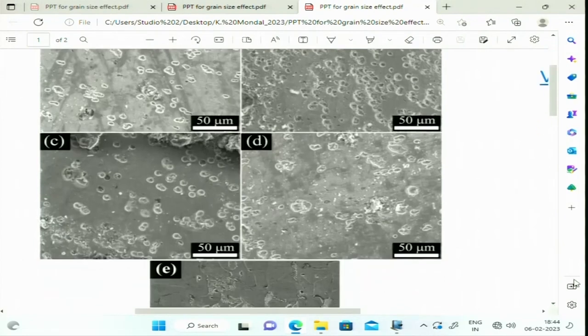But if you compare with the as received one, the number of pits in case of 18 micrometer, which is the C image, is larger than the as received one. But once we go to a bimodal structure, which is fine and coarse grain, we could see the pits are there, but the number density of pits has reduced compared to the 18 micrometer grain size material. So it gives an indication that if we go to fine grain, we can increase the number of pits, and since the only change brought about is the grain size, the grain boundary area has increased. Of course, there will be a little strain here also, because at 4 micrometer the strain is not completely relieved, but still the majority effect is coming due to the grain boundary area enhancement.